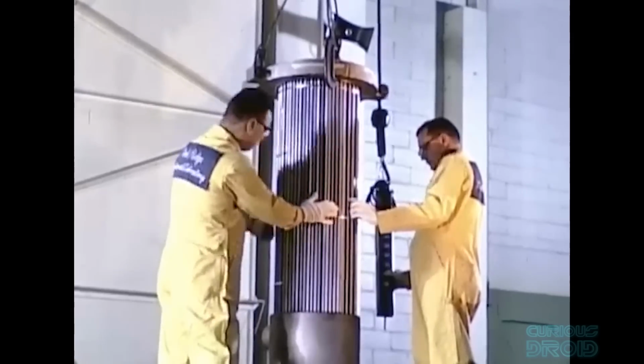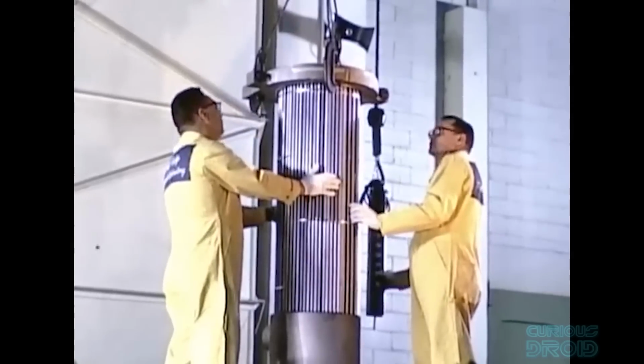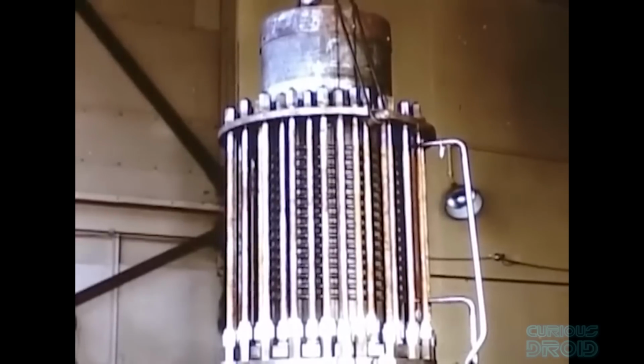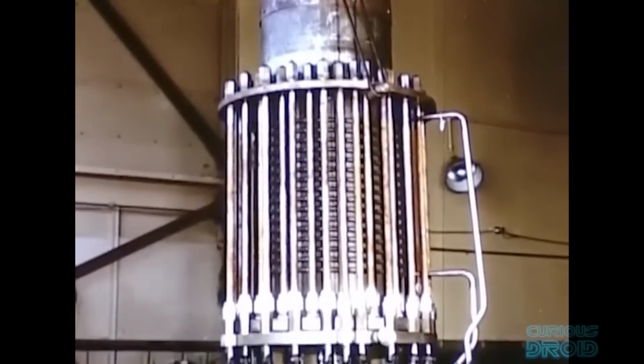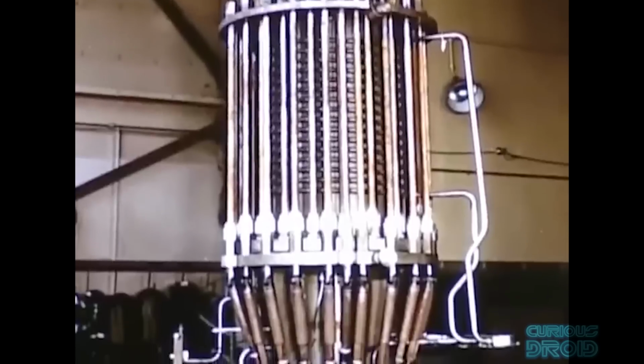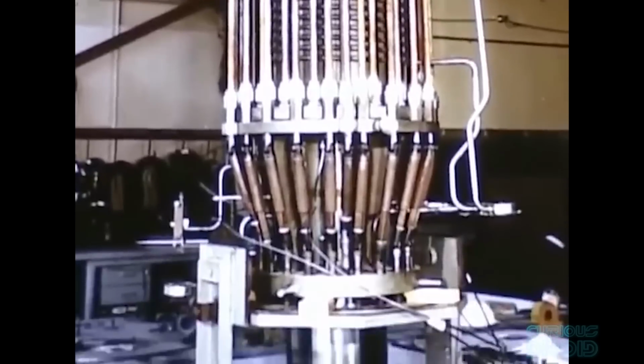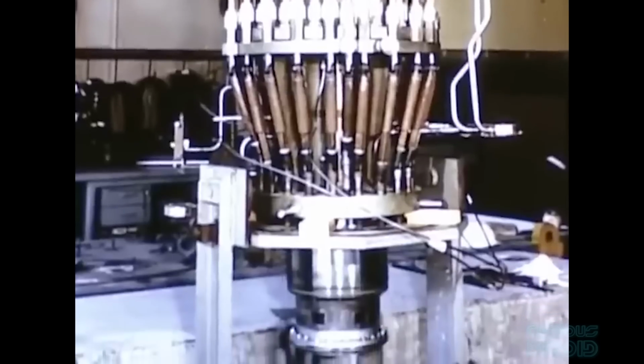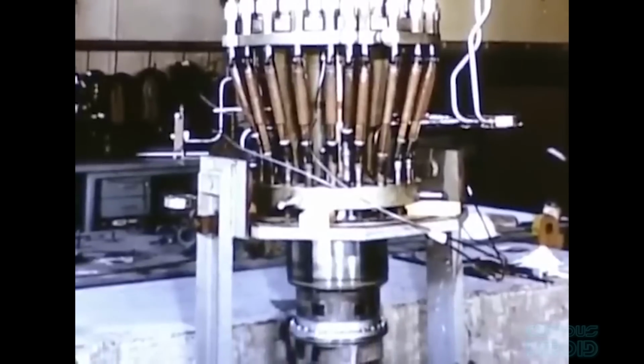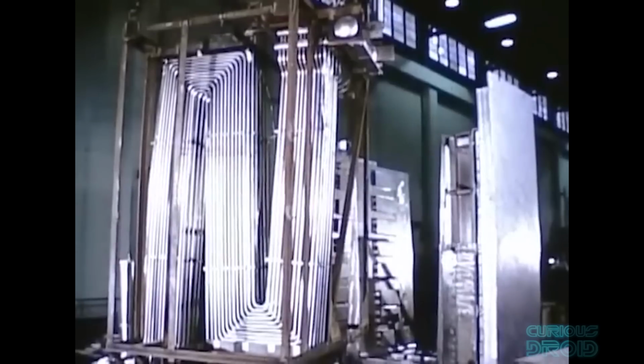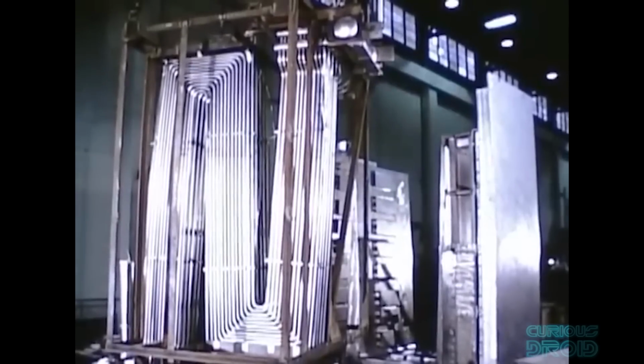While this was enough for the experimental reactor to last 4 years, in a commercial reactor it might be expected to run for 40 to 60 years. And this became the Achilles heel of the molten salt reactors. If the metals that make up the reactor start to fail after maybe 5 to 10 years, it would not make for a viable commercial reactor.